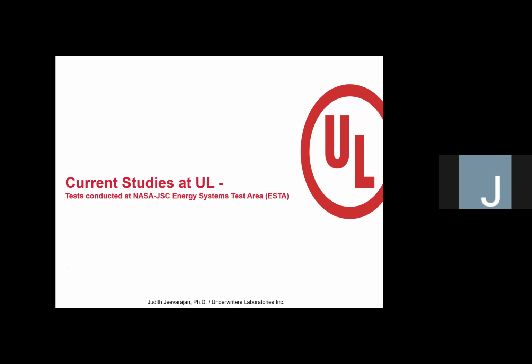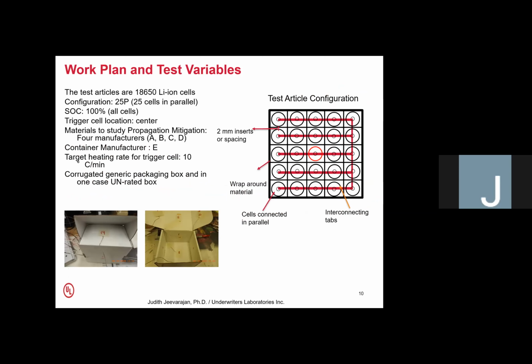So continuing on that work, which was just preliminary, like I said, we were looking at different materials in the past year and a half. Our test article is 18650 lithium-ion cells, and we're looking at a 25p configuration, because that is really worst case. When you have cells in parallel, you're going to be conducting between the tabs, and also if there is an imbalance in current, they're all at 100% charged, but they're not being charged or discharged during the test. So all the conditions are worst case, I should say, and we were looking at triggering a cell in the center of the configuration with heating tape.